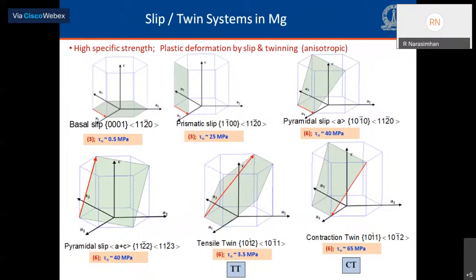Contraction twins, on the other hand, remain typically narrow. Both of these involve very large rotation of the crystallographic lattice when they take place. Now, if you examine the critical resolved shear stress values, which I have listed here, you would note that basal slip and tensile twins have very low critical resolved shear stress. They are soft deformation modes, whereas pyramidal C plus A and contraction twins, on the other hand, are hard deformation modes.